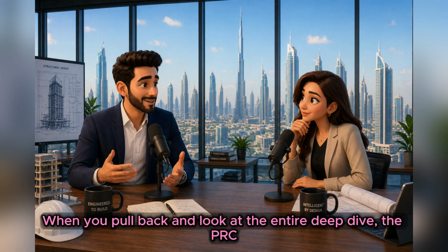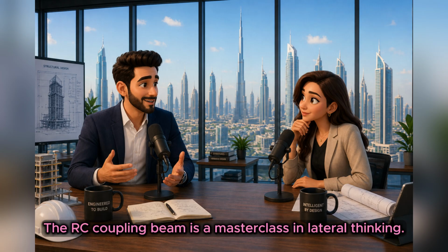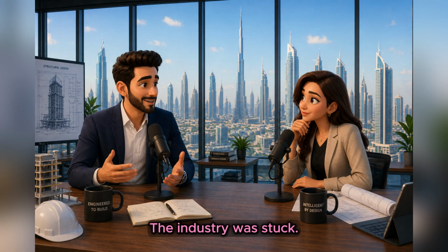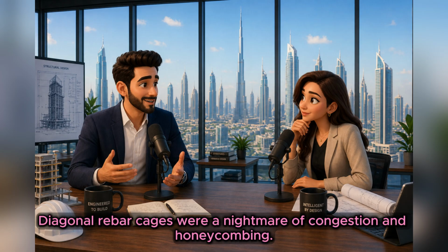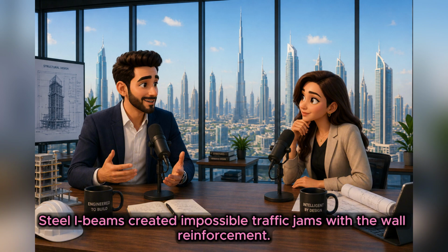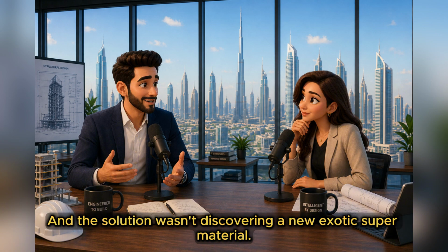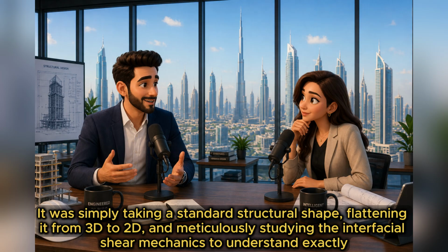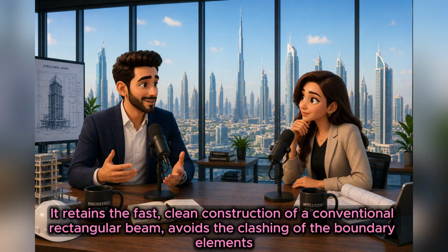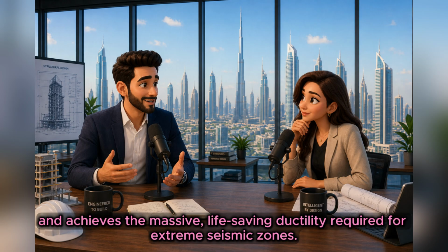When you pull back and look at the entire deep dive, the PRC coupling beam is a masterclass in lateral thinking. It truly is. The industry was stuck. Conventional concrete pulverized itself. Diagonal rebar cages were a nightmare of congestion and honeycombing. Steel I-beams created impossible traffic jams with the wall reinforcement. And the solution wasn't discovering a new, exotic supermaterial. It was simply taking a standard structural shape, flattening it from 3D to 2D, and meticulously studying the interfacial shear mechanics to understand exactly where to place those headed studs. It retains the fast, clean construction of a conventional rectangular beam, avoids the clashing of the boundary elements, and achieves the massive life-saving ductility required for extreme seismic zones.